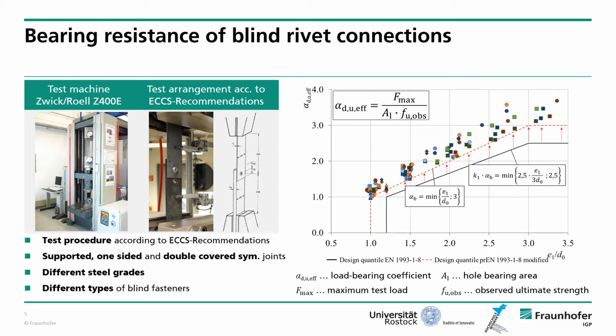And if we now compare this value of the load bearing coefficient with the design quantile according to the Eurocode 3 part 1-8, we can see all test results are above this design quantile, so we can sum up that the design rules for bolted joints or connections according to the Eurocode 3 part 1-8 are also applicable for blind rivet connections in this case, where we have a bearing failure of the sheet material.